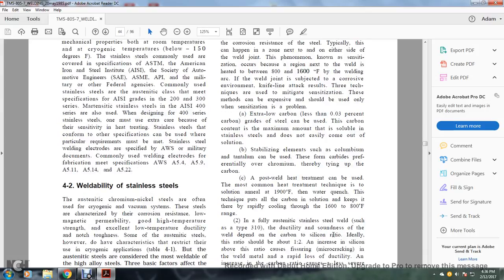C. Post-weld heat treatment can be used. The most common heat treatment technique is the solution anneal at 1900 degrees Fahrenheit, followed by a water quench. This technique puts all the carbon in solution and keeps it there by rapidly cooling through the 1600 to 800 degrees Fahrenheit range.